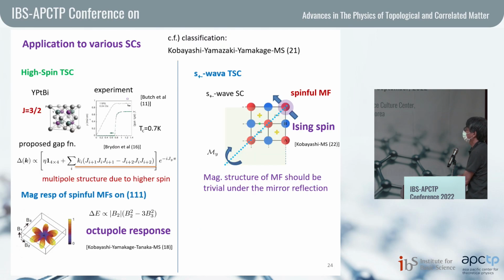So finally, I'd like to apply this argument to various superconductors. Actually, we have a complete classification in this paper, but in this talk, I explain two particular examples. The first one is the high spin topological superconductors. And in this case, I consider yttrium platinum bismuth. And this is a well-known high spin superconducting state. And the experimental results show superconductivity at low temperature, and it also shows the presence of line nodes.